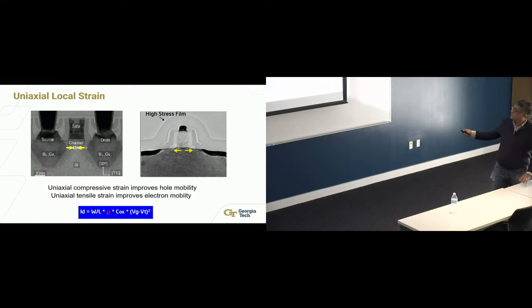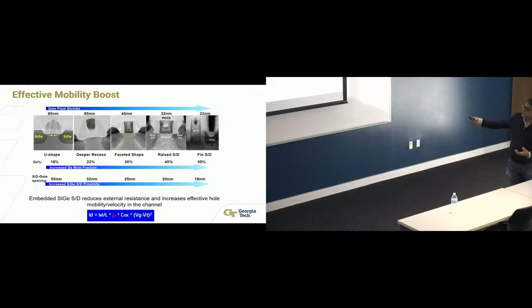On the NMOS side, what was done was to create a very high stress nitride film on top of the gate, and that, like a Saran wrap, is trying to expand out, and as it tries to expand out, it starts pulling out here and pulling out here. So you take advantage of this topography of the drain and try to engineer the strain locally. That was the key breakthrough that Intel came up with, and of course, everybody adopted this. It was to increase the effective mobility of the transistors.